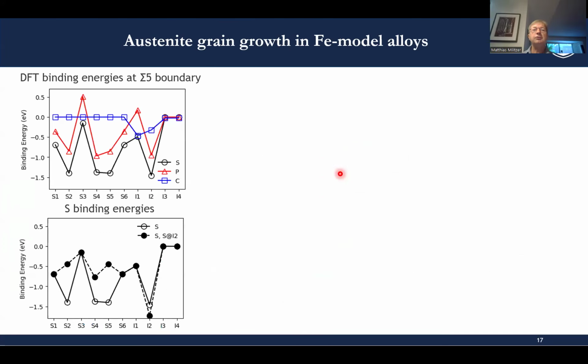And we can do the DFT calculations for binding energies at the sigma 5 boundary in FCC iron. And we see that sulfur is the element with the highest binding energy, followed by phosphorus and then carbon. What is important to realize is that the sites called I1, I2 are interstitial sites at the boundary. And sulfur and phosphorus, even though they are substitutional alloying elements, at the grain boundary prefer to segregate to the interstitial site. So they compete with carbon, which obviously only segregates to interstitial sites.